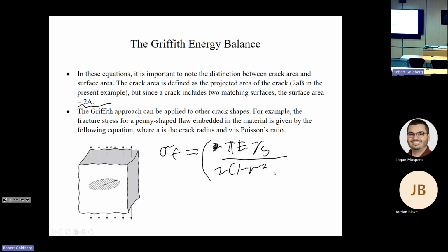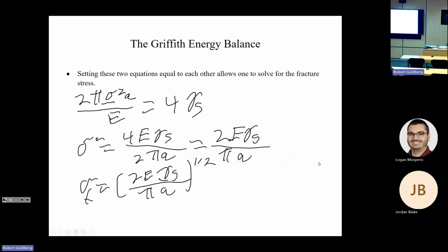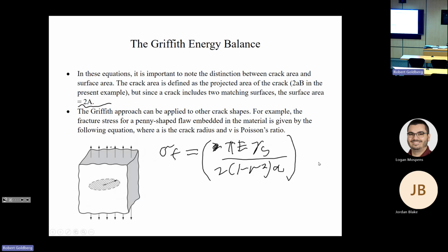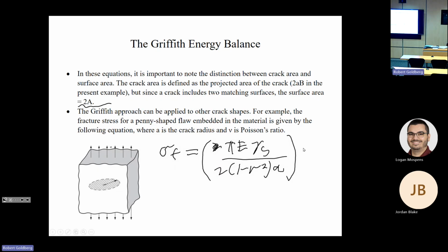Now the difference is we have this extra term in here, related to the Poisson ratio. So you see, this is pretty similar to what we just developed. The difference is we've shifted where the 2 is located. In the original equation, the 2 was in the numerator for the sharp crack. Now for the penny-shaped crack, the 2 is in the denominator, and we also have this extra Poisson ratio term in there.